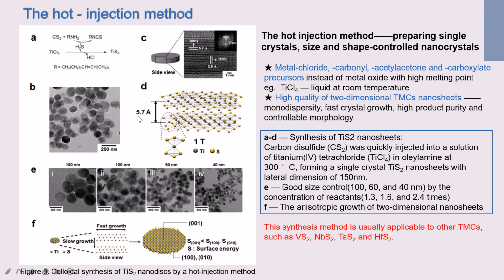As shown in Figure A to D, in the synthesis of titanium disulfide nanosheets, carbon disulfide was quickly injected into a solution of titanium tetrachloride in oleylamine at 300 Celsius, forming single crystal titanium disulfide nanosheets with lateral dimension of 150 nanometers. And also, figure E shows good size control by the concentration of reactants. Figure F shows that the anisotropic growth of 2D nanosheets is attributed to the large surface free energy difference between the edge and the base surface. This synthesis method is usually applicable to other TMCs, such as vanadium disulfide, niobium disulfide, and tantalum disulfide.